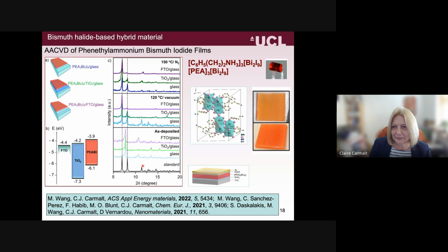We've been interested in bismuth halide-based hybrid materials. So here we use this complex shown here. So we made this iodobismuthate compound, and we chose to use this large cation. It's an ammonium cation that's quite hydrophobic. This is the crystal structure, and you can see you form these beautiful crystals. And you can then use this in AACVD, and you deposit a film, which is shown here, which on annealing then looks like this orange film shown here.